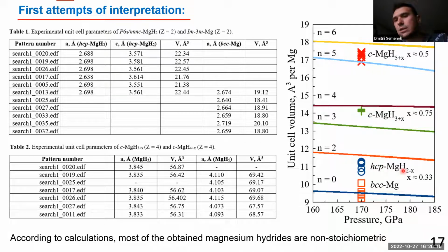Magnesium H2 has lower volume. I don't completely understand why it is so, but I just show the experimental results I have. And for magnesium H3, it's different places, a little bit different pressure, so that's why, and different quality of X-ray diffraction data. But I think the average value is more or less close to the theoretical prediction for BCC magnesium.